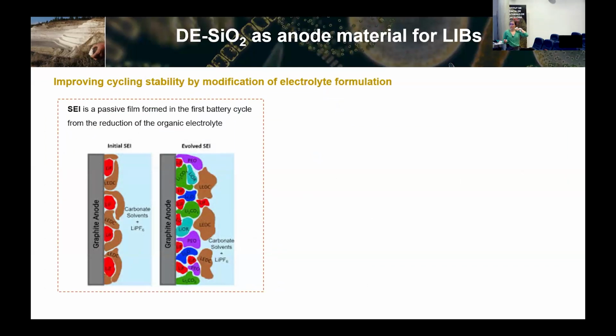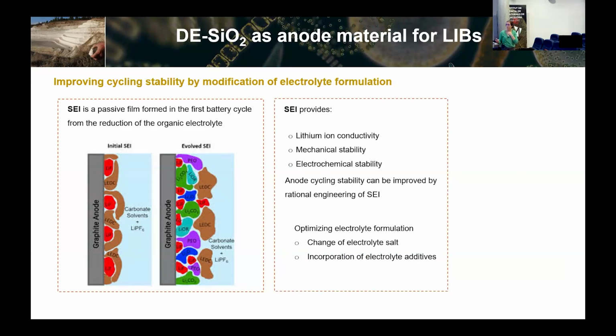So then we try to work a bit on trying to improve the solid electrolyte interface to see if we could improve a bit the capacity. That's something you will do with the silicon anodes, but has not been done for the silica one. So basically, as you might know, SEI is quite important for keeping good cycling stability, for having good lithium diffusion path, and also for the mechanical stability of the anode.